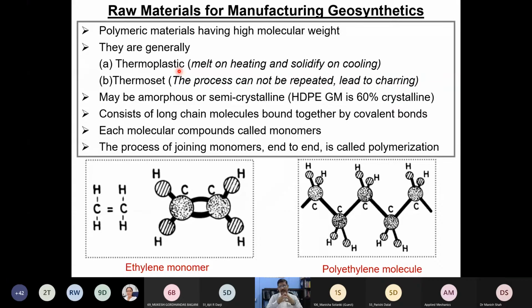Thermoplastic means that when you heat them, they melt, and upon cooling, they solidify. On the other side, with thermoset plastics, you cannot really repeat the same process. If you keep on heating and cooling, during the heating they may lead to charring of the polymer. That means thermoset polymers may be subjected to degradation when you heat them up. As a result, the polymer structure may get altered over a period of time. So we are more interested in knowing about thermoplastic polymers.